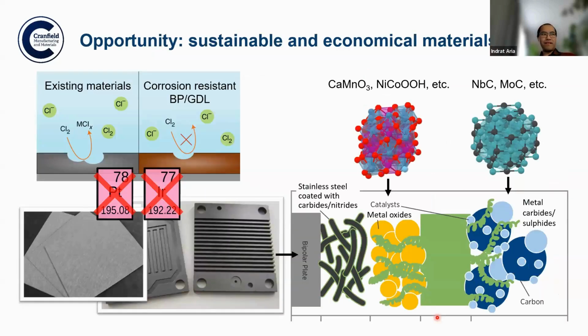The last bit I want to talk about is the activities that I have been doing in my lab. Because of these challenges, the high cost and the unavailability of platinum group metal and the high consumption of nickel for catalysis, in my lab we focus on other abundant materials that are free from platinum or iridium for both the catalyst and for the coatings. So we want to replace the platinum, for example, with niobium carbide, molybdenum carbide that are more abundant and cheaper. We want to replace the iridium with calcium manganese oxide or nickel cobalt oxyhydroxide that are again much cheaper and more abundant.